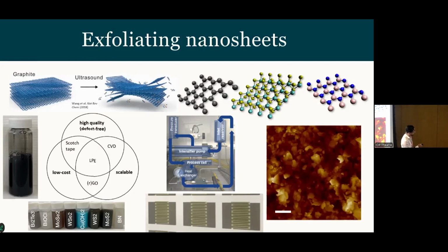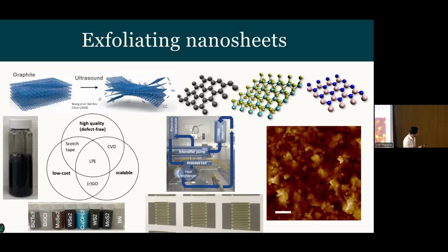And when we go in with the AFM and look at what these networks look like, they are locally very disordered. So we heard about single crystals and polycrystalline materials. These are another extreme or the next level of disorder in these systems. They're particulates. They have junctions between them that I'll talk about. Those affect the behaviors. But over longer length scales, they're actually quite uniform, or the disorder repeats over. So we can start to understand the properties of these ensembles.